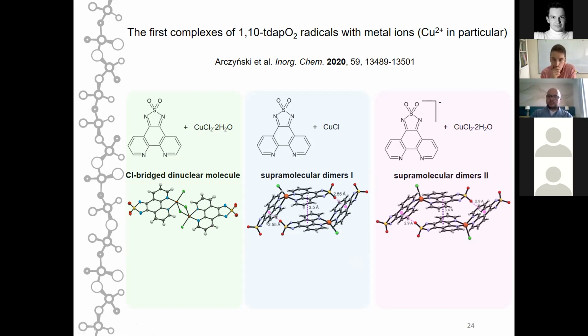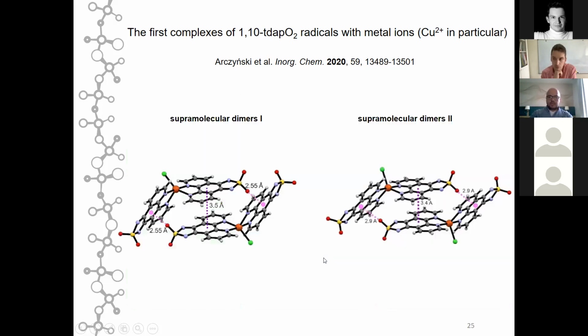And if you combine the neutral anions with copper 2, you actually end up in a different type of supramolecular dimers. And I'm going to show you what's the difference. First of all, these supramolecular dimers are very similar despite a completely different synthesis. There are also very peculiar interactions here between the pi-acidic central ring of the ligand and the SO moiety of the dioxothiadiazole, which persist in both supramolecular dimers.